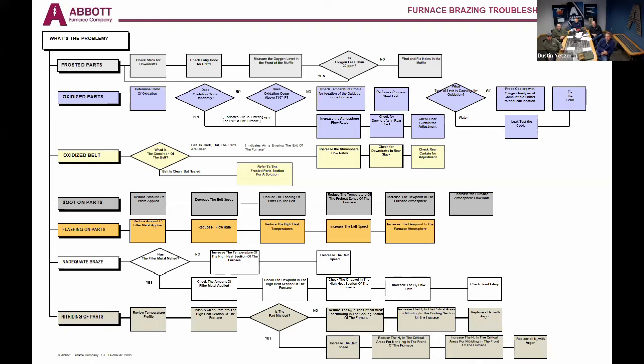Sometimes it's just an inadequate braze. So, where you're checking mechanical strengths or pressure testing, a lot of times that can relate back to temperature profile maintenance. Is that filler paste melting through the joint? Are you getting good flow of material? Sometimes that's related to belt speed and throughput in the furnace, depending on the load. Sometimes we need a little more hydrogen flow in that situation to help that joint get cleaned up so that the paste can wet through and actually finish the braze.